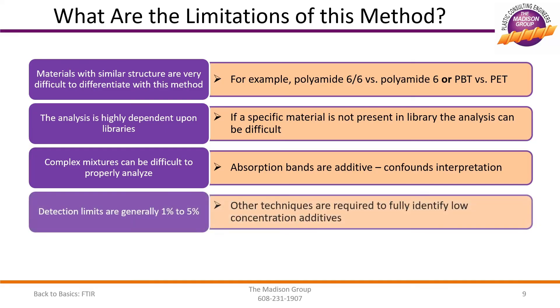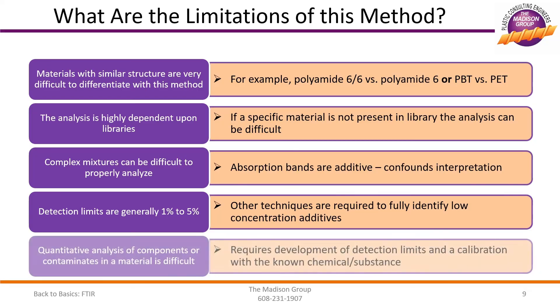Detection limits for most additives are generally between 1 and 5 percent, and therefore may require additional test methods to identify. Finally, quantification of components is difficult with this method and will require significant method development in order to get accurate results.